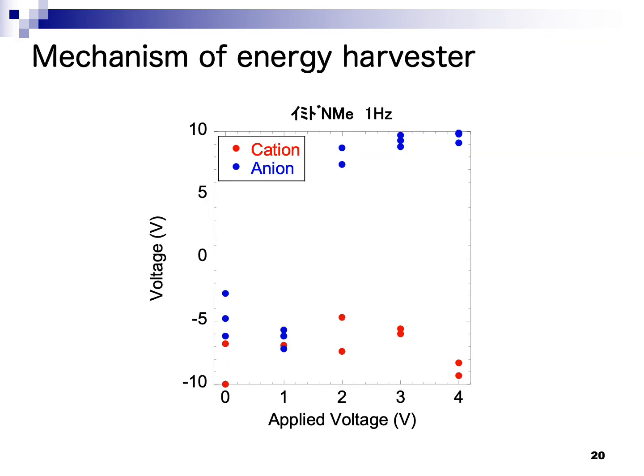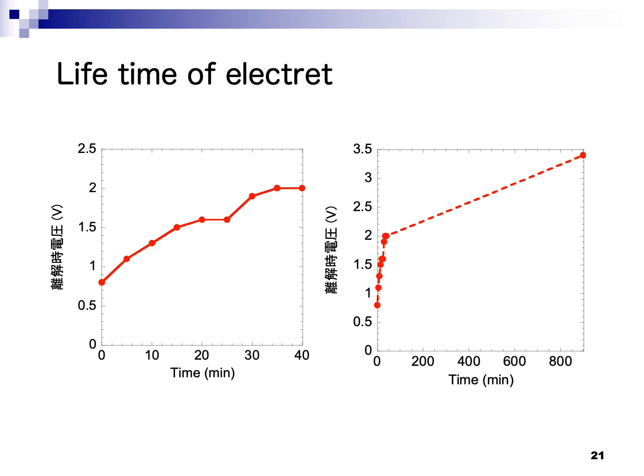Another thing is that this material is air stable, because we recently used a fluorine terminated ionic liquid, and there is a strong repelling of water from the surface of this electret.